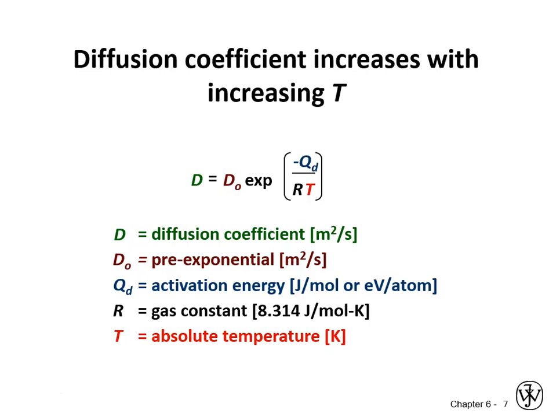This should look very, very similar to the equation for vacancy concentration, because your diffusion coefficient, or your activation energy in this sense, at least in the case of substitutional diffusion, is in fact partially dependent on the vacancy concentration, the landing place.